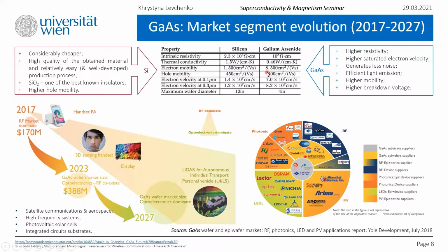For now, gallium arsenide has a poor hole mobility. The key technology in the computer chip now is CMOS, where you have the N-type and P-type transistors together to form logic gates. And the currents through the N-type and P-type devices have to be balanced in order to have a well-functioning device. Otherwise, you get difficult timing issues and others. And in order to balance the current, you need somewhat of a balance of electron and hole mobilities, because you'll need to use the same properties on gate widths in order to balance the current.